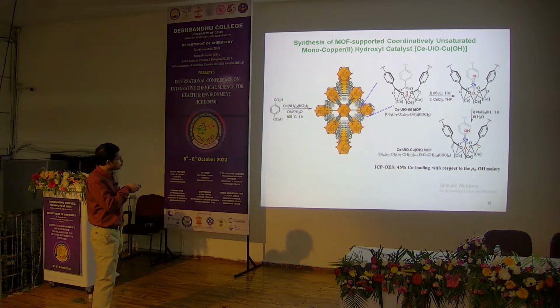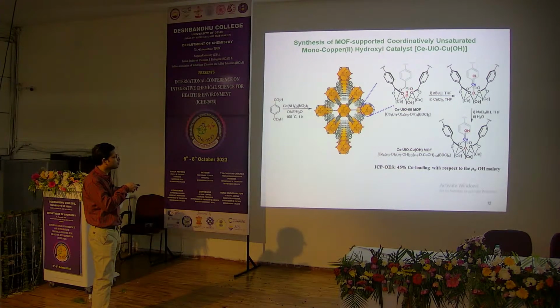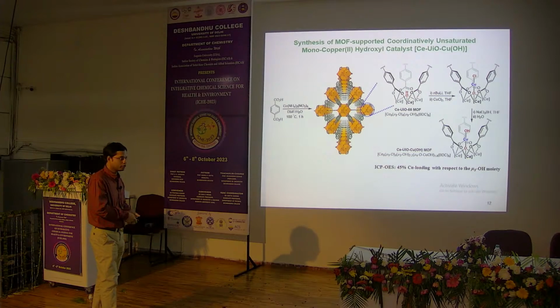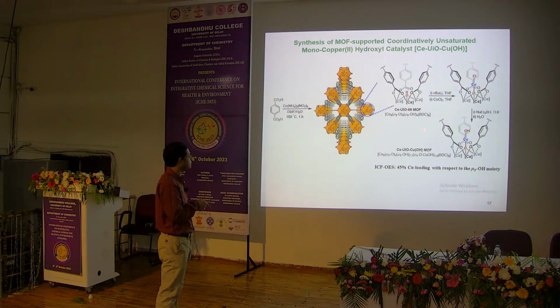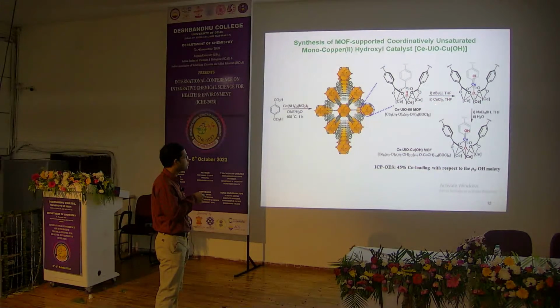So if we just zoom in on these secondary building units, this is the secondary building unit. It is composed of cerium 4+ ions, oxo and hydroxo, and these are the bridging units. And there are mu3 hydroxyl groups which can be used for further catalyst development. So in the next step, we treated with a base, n-butyl lithium, at room temperature in THF to deprotonate these hydroxyl groups, then simple metallation by a salt metathesis route by treating with copper dichloride to give this MOF node supported single site copper chloride species.